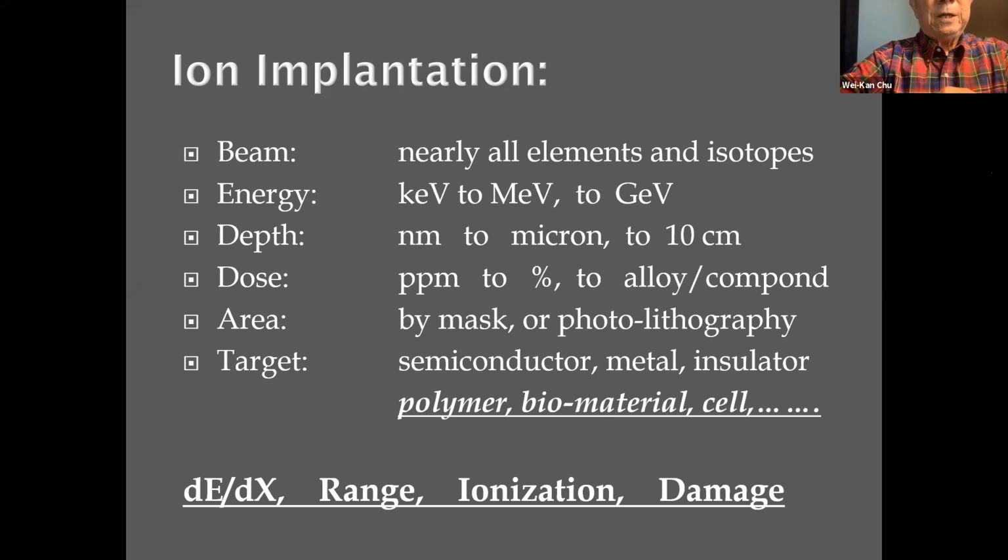What he did is he has a mask with a very small, tiny hole. Then he sends the phosphorus beam through this hole, but the beam is very, very weak. Therefore, the phosphorus doesn't flow like a water faucet, where you turn it on and it just zooms. No, it becomes a drip, almost atom by atom.